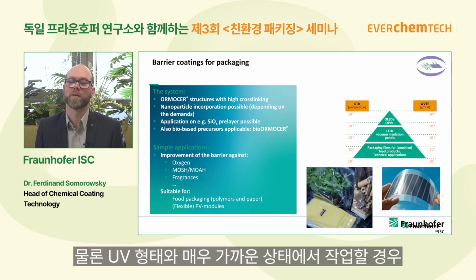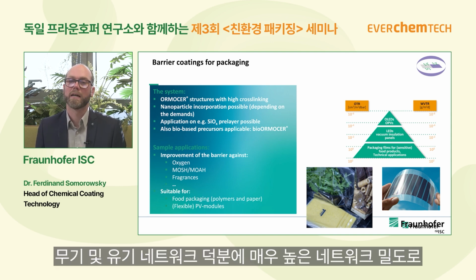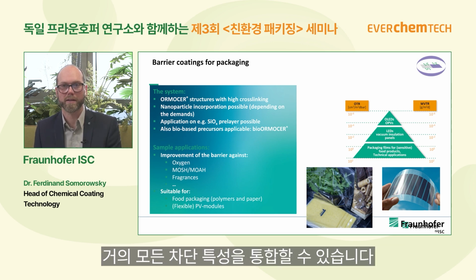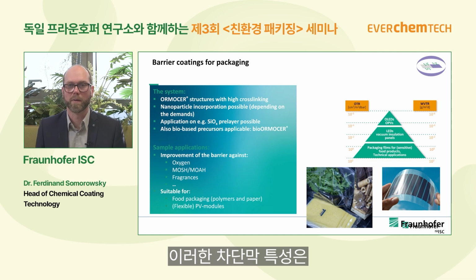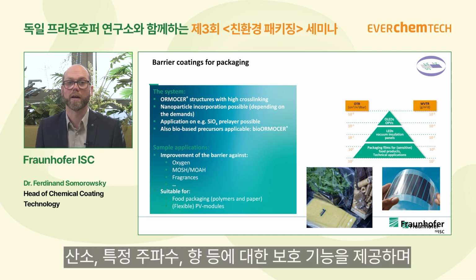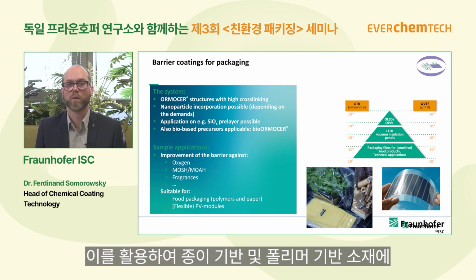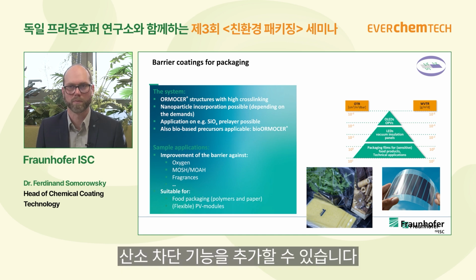Of course, the barrier. We work together very closely with the Fraunhofer ISC, and we can integrate the barrier properties into the ORMOCER due to this very high network density. Due to this inorganic and organic network, we have a barrier towards oxygen and also fragrances and aromas, and can equip paper but also polymer-based materials with an oxygen barrier.